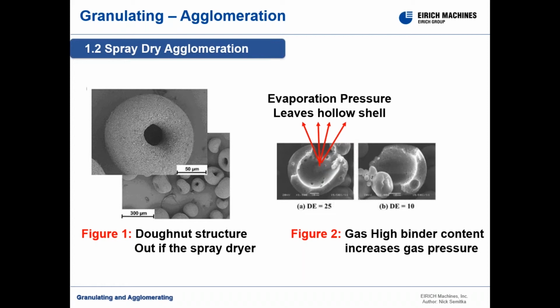The structure of these granules resembles a donut, as shown in Figure 1. This occurs when there is a high moisture or binder content. Additional slurry coating fills these cavities and increases the granule size. Figure 2. If the binder level is too high, the evaporation pressure inside the granule increases until it explodes, producing a hollow shell. This may affect the preceding process, causing defects in the final product.